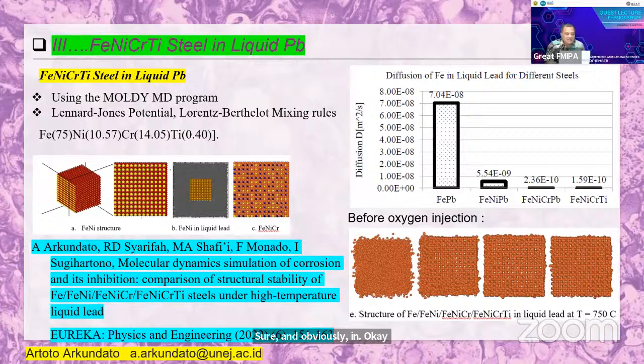And then my third research is about steel, iron, nickel, chromium, and titanium, which I put in the center of liquid lead. We can see here, if we only have iron without the others, so there is pure iron, not steel.